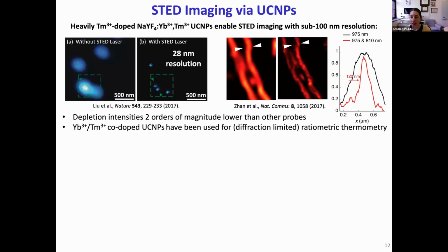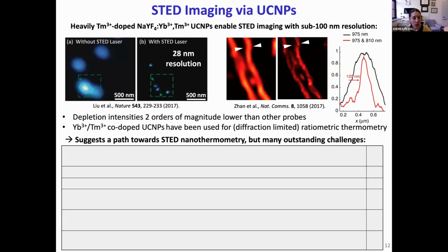So this work was really exciting to me for a couple of reasons. First, UCNP-based STED uses depletion intensities 2 orders of magnitude lower than other probes. And second, ytterbium and thulium co-doped UCNPs had separately been used for ratiometric thermometry in a conventional diffraction-limited mode. So taken together, these advances suggested that there was an opportunity to adapt STED imaging for nanothermometry.